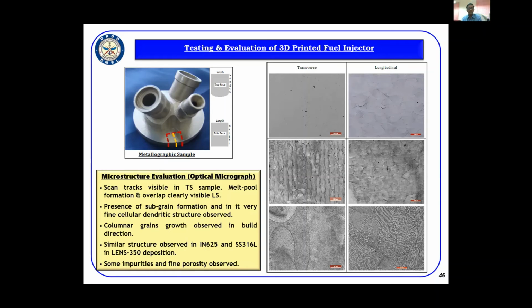Then we have carried out further evaluation to understand the metallurgical aspect of this material deposition. We took a small piece from the component and looked at what sort of microstructures were obtained in both the transverse direction and the longitudinal direction. In the transverse direction, we could see the scan tracks very clearly, and the melt pool formation is also very clearly visible in the longitudinal direction, as shown here in each layer.